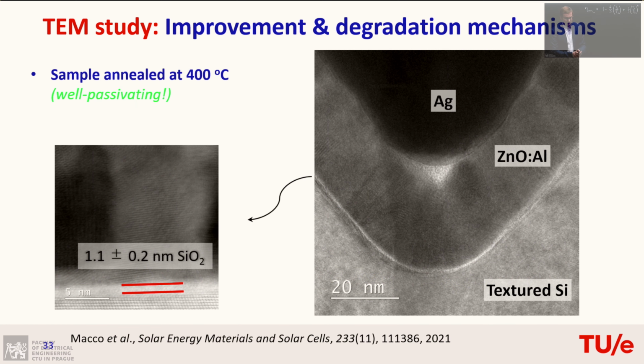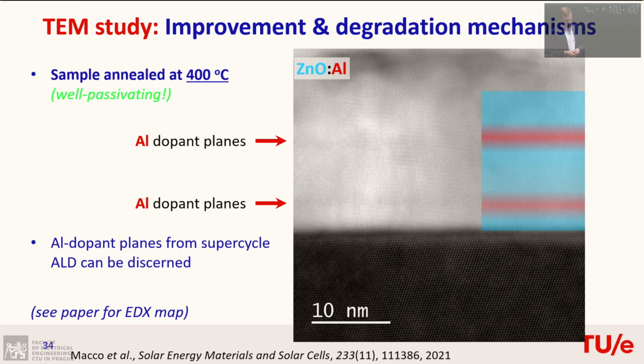Then I'll try to understand these nanolayers a little bit better. So we use TEM actually to see what's going on. We have, in this case, at 400 degrees annealed, a sample that's very well passivating. We have textured silicon and a very thin interfacial silicon oxide layer. And then we get a zinc oxide over here, and then some silver over there. So what you see already from the growth process that I showed before, where you have your zinc oxide matrix and your aluminum planes in between, you can really see on the microscope that it is also there. So these aluminum dopant planes, they are over here. So that is nice actually, that it confirms that the growth is like that indeed.